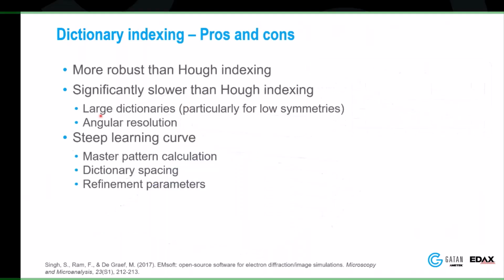But there are some pros to the dictionary method, and the main thing is it's more robust than Hough. While it is definitely slower, it is much more robust, specifically with low quality patterns, lower symmetry materials, and deformed materials. Dictionary indexing has its place. I think the craziest data set I've seen for dictionary indexing, and I know a lot of geologists are here, involves a process called shot peening, which is shooting metal balls to toughen the surface of materials.